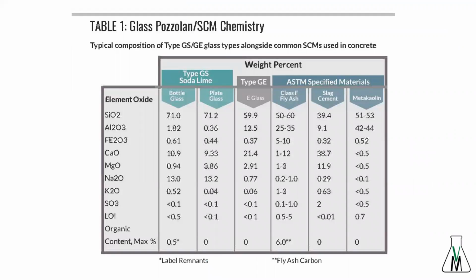So when you look at the different chemistries of the glass pozzolans, the type GS have one unusual characteristic, and that is they have high alkali content. And this kind of prevents them from acting as mitigators of alkali silica reaction. However, the type GE glass has a very low alkali content, and it's an excellent pozzolan, can be used exactly like Class F fly ash, except that it's white instead of dark in color. Let's look at the next slide.